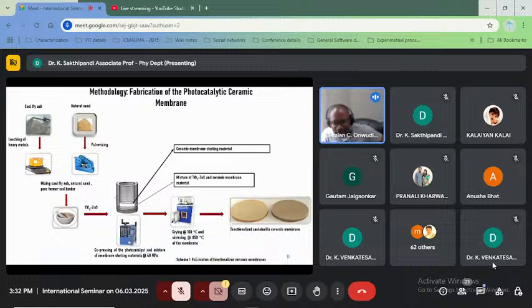In this study, we use titanium oxide and zinc oxide to coat the surface of the ceramic membrane. That is why if you look at the ceramic membranes, the one on the left, the surface is lighter because it contains nanoparticles. The one on your right is darker because it is not coated. Next.